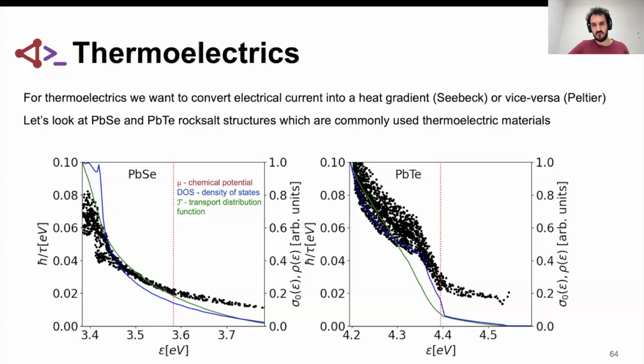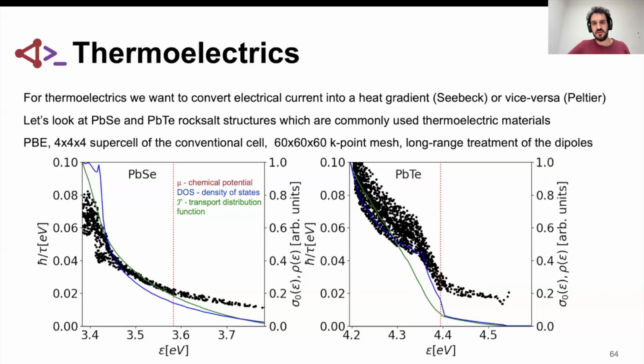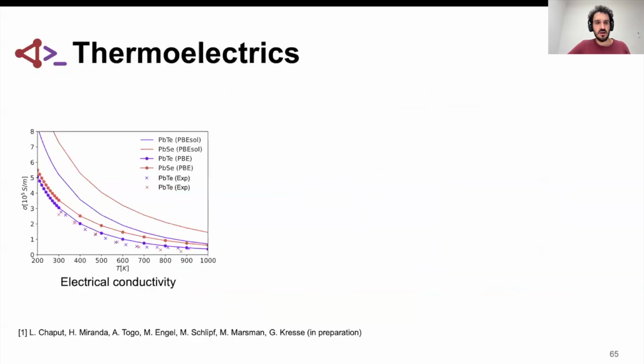So these are all VASP calculations. These are some parameters that were used to run the calculation. We can obtain electrical conductivity and compare with experiments, and the agreement is good. Of course, we are not considering other scattering mechanisms such as defects, which do play a role in these materials, especially when comparing with experiments.